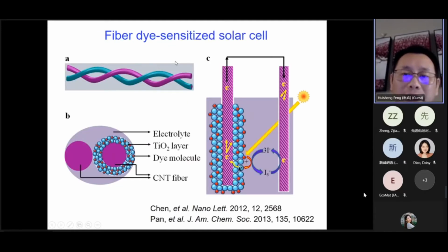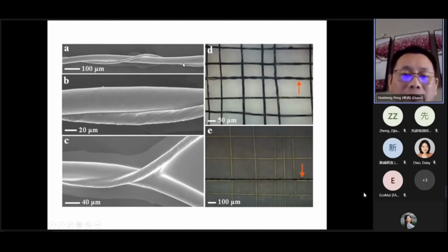Okay, I will show you several examples of these solar cells. First I will show you the dye-sensitized solar cell in fiber shape. Here is the structure, one fiber electrode, and here is another fiber electrode, and we use dye molecules as the active layer on the surface of one fiber electrode. Then we twist them together, and we can have this fiber device. For fiber solar cells, it's very important that one fiber electrode be very flexible. Otherwise, if two rigid fibers are twisted together, the interface will be very poor, and then it will be very difficult for charge transport at the interface.